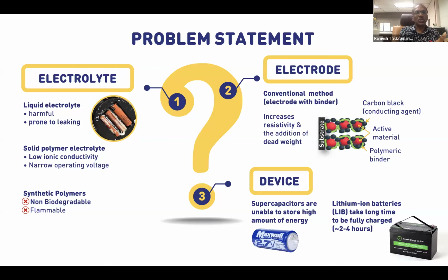But the problem here is when we make solid polymer electrolytes and sandwich them with the electrode material, the contact can be an issue as well. So this will create low ionic conductivity, and this will lead to lower performance of the devices. When we talk about the electrode, the conventional method is using a binder. The famous binder they use is polyvinylidene fluoride, PVDF, which is also insulating. So these kinds of materials increase the resistivity and also add dead weight. So that is where we are promoting the binder-free electrode. So we see how to overcome the electrolyte, electrode, and also the device. The device part, I already explained to you earlier.